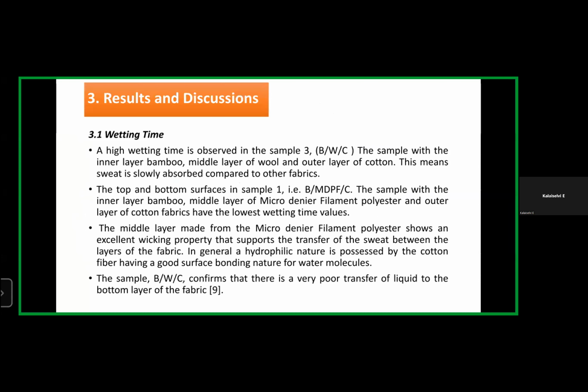These are the results after testing for moisture management property. The wetting time is observed in sample 3. A high wetting time is observed in sample 3, the sample with the inner layer bamboo, middle layer wool, and outer layer cotton. This means the sweat is slowly absorbed compared to the other fabrics.